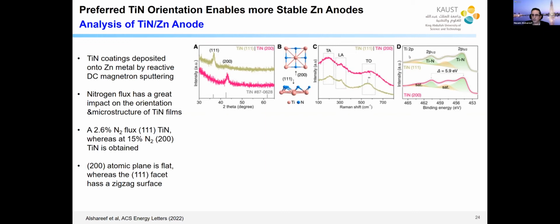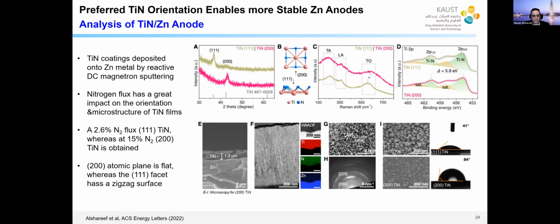And if you look at the orbitals, titanium 2p in XPS, you see that they confirm that we have titanium nitride with the spin orbit splitting here. This material, if you look in the SEM, here is how it looks like, covering zinc. And if you actually zoom in and do some compositional analysis, you see the titanium and nitrogen here, and you see the zinc. So this confirms this is titanium nitride, and this is the zinc. You can zoom in and see its microstructure, and you will see that these different atomic arrangements result in different surface energies, and the contact angle on these two materials is different.